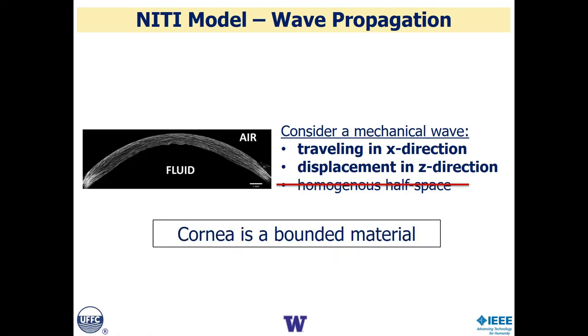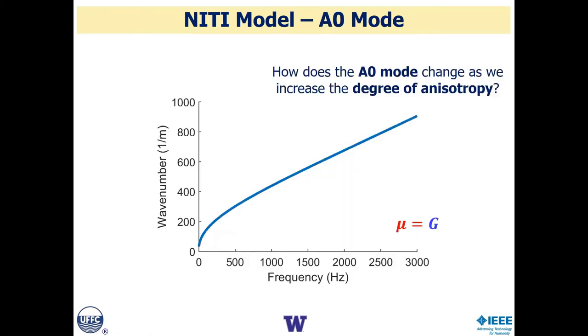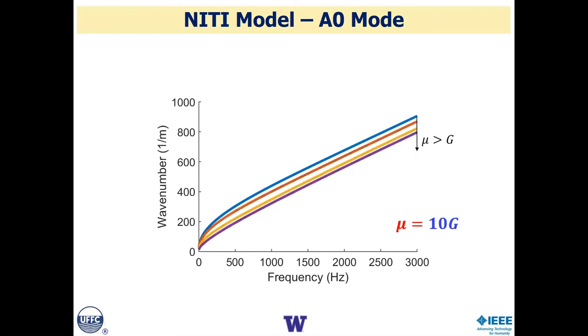However, for the first time in my life, a bug became a feature, because the cornea is a bounded material, it's not infinite. It means that you can have coupling between the different polarizations of shear wave due to the reflections off the boundaries. And so in that case, the lowest order mode, the A0 mode, couples polarizations and therefore couples information about the 2 moduli. So you'll find that the mode structure changes based on the anisotropy factor.